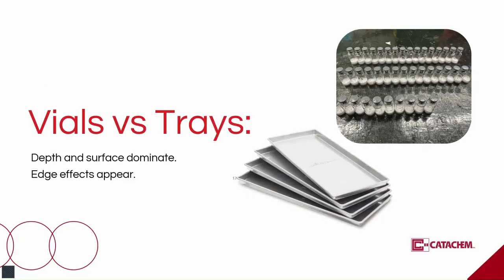Fill depth increases resistance to sublimation. Edge effects can be pronounced. Thermal gradients across the tray can create zones where product temperature and drying rate diverge. Scaling is not same recipe, just bigger. It is engineering a pathway that recreates the same product conditions, especially product temperature relative to collapse temperature across a different geometry.